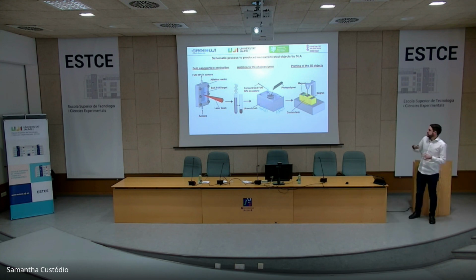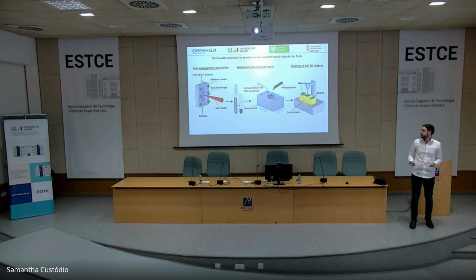We take this new material, and the extra thing that we did was modifying the printing setup. Usually this printing technology is based on UV light that is coming from below, and we have a tank with the photopolymer. And then this UV light is basically solidifying the photopolymer in the area that it is interacting with. What we did was to add some magnets on the side of the printing tank. Why the magnets? Because this is doing some orientation of the nanoparticles.